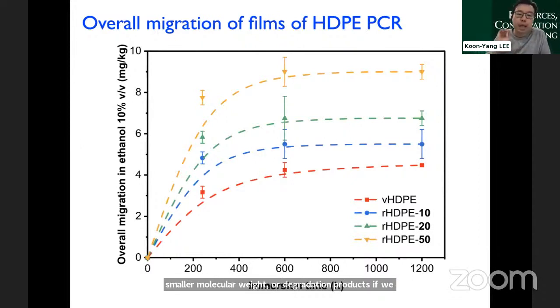So here I'm only showing you our films, our high density polyethylene post-consumer recyclate. So the ones in 10% ethanol, so not a very harsh system, basically just a little bit on the stronger beer side of things. So virgin polyethylene, you will still see some form of migration of molecules, most likely smaller molecular polyethylene molecules, but it's only 4 milligrams. So it's actually very, very tiny per kilogram of material, very, very small amount, right? But those with increasing number of recycling, right, you're actually increasing this migration of small molecules into the solution. And that is actually something expected, but also something that you do not want happening.